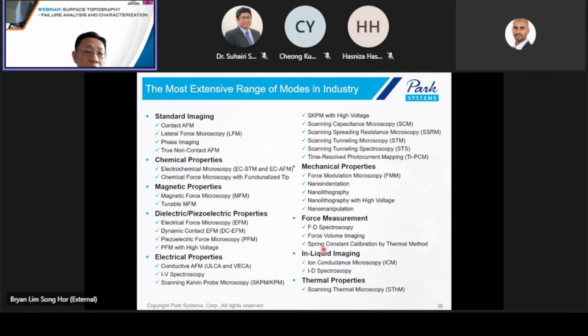Okay, so in short, there's a lot of modes for AFM. Other than the standard topography imaging, we can also measure chemical properties, magnetic, piezoelectric properties. If your sample has ferroelectric domains, electrical properties, we can measure IV curve. We can also measure mechanical properties like nano indentation. We can also do some nanolithography on the sample surface. We can do force measurements. And AFM can also scan in fluid environment as well. So it's a very versatile tool for research as well as failure analysis.